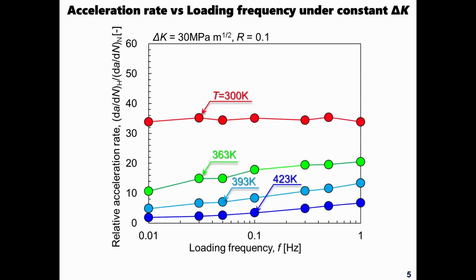This figure shows the loading frequency dependence of the relative acceleration rate of fatigue crack growth for various temperatures at constant delta K, 30 megapascal square root meters. First of all, looking at the data acquired at 300 Kelvin, no loading frequency dependence occurred, with a constant relative acceleration rate around 35. But at the highest temperature, we found a critical loading frequency dependence. The other temperatures showed apparent loading frequency dependence as well.